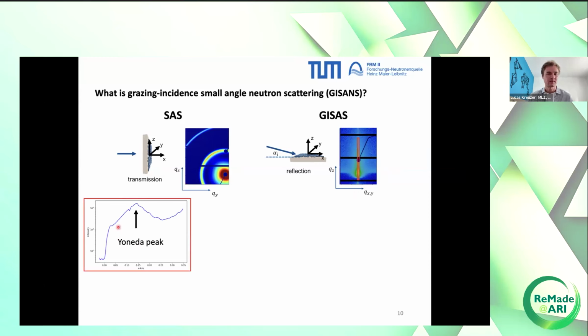which, for example, looks like this. It has one prominent feature that is called the Yoneda peak. This is at a QZ position that is slightly above the total reflection. So we are just at the right angle that the first neutrons can penetrate the film. Then you have a certain effect of an evanescent wave underneath the film surface. And this leads to an amplification of your scattering signal. And this is then called the Yoneda peak.